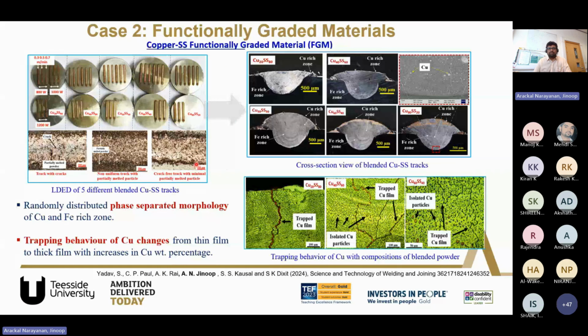Then also recently, one of my previous colleagues, Sunil Yadav, we worked together on a project on using copper stainless steel FGMs. It's really challenging because of the poor solubility and immiscibility in liquid phase of copper and Fe, and again rapid solidification in LDED results in randomly distributed phases, phase separated morphology in the melt pool. So trapping and segregation was observed a lot.